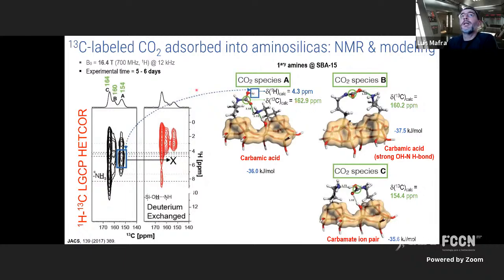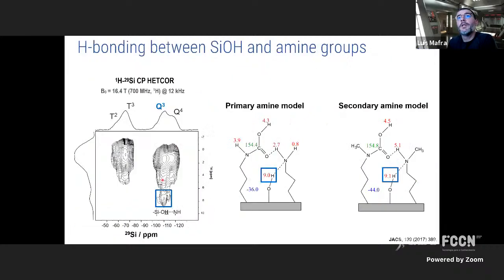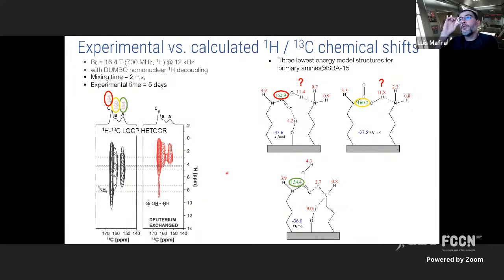So as you can see, carbon chemical shifts fit quite well the experimental data, okay? And we can even see this peak here, this deshielded peak, which can also be observed in proton-silicon correlation spectra. And this is due to the existence of silanols that have not been grafted. We have some silanols here that can hydrogen bond. So this is also the first proof of hydrogen bonds between the surface walls and the amines that are grafted.